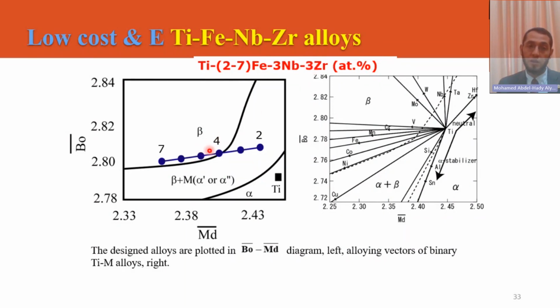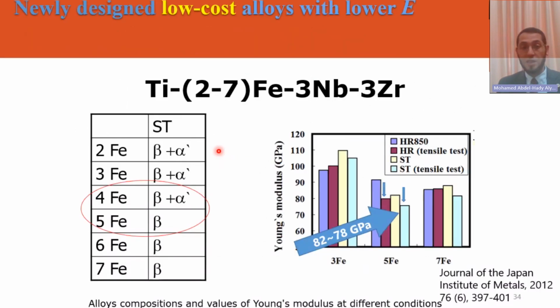According to our prediction here, from the composition point of view, alloys 4 and 5 are promising to show the needed low elastic modulus and so on. As expected and as planned from the composition, this is experimental. As a function of iron content in this alloy system, yes, this composition will show a phase stability transition from beta phase to beta plus martensite. And the lowest elastic modulus is achievable at this composition. This is at 5 iron.